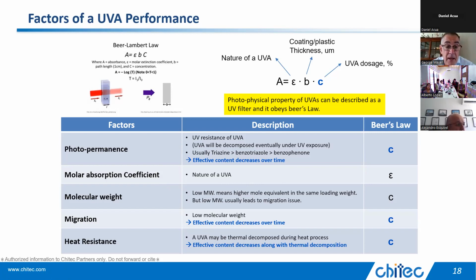So then people don't like that because it introduces kind of a yellow or even red color if you go too far up. Molecular weight really is related to the migration or heat resistance. A really big molecule will not sublime out of your coating and go away. So big is better, but it also dilutes the good chromophore. So the really big molecular weight UV absorbers usually don't have as good a molar absorptivity as the smaller ones. So that's kind of a compromise consideration.